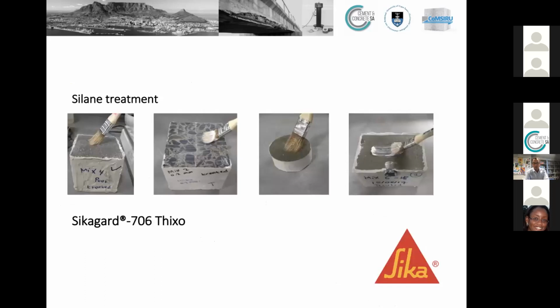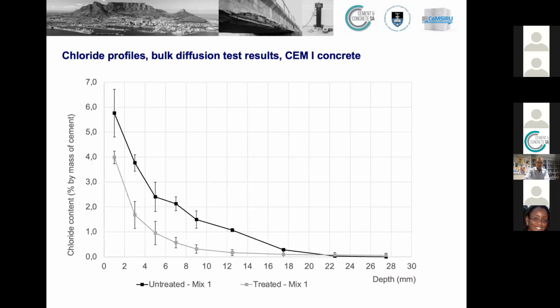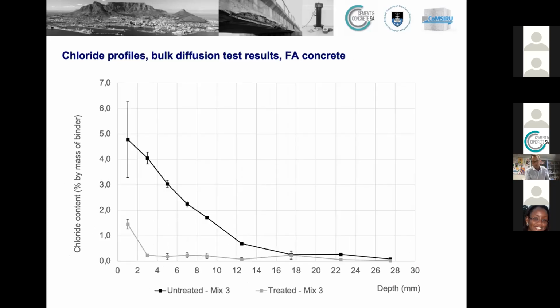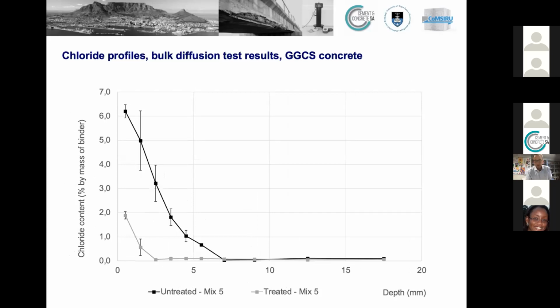We used a Sika product. This research was sponsored by Sika, and measured bulk diffusion, meaning we put concrete samples, treated and untreated, and different types of concrete samples in a chloride bath and measured chloride ingress with time. These are the test results. So here you can see chloride ingress into a CEM I concrete, OPC concrete. The black curve is the untreated sample, and the gray curve is the treated sample. And clearly you can see we have got much lower chloride ingress into the concrete that has been treated. This effect was much more pronounced in fly ash concretes and also concretes containing Corex slag.